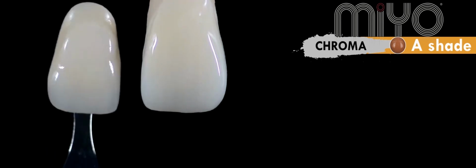Okay, and I'll be using translucent A here. You could see me float the color on top of the existing glaze paste. So there's different methods of MiYO application. Here I'm showing one application method by putting a thin layer of glaze paste before all the colors, because my intention is to glaze and finish everything with one shot. So you could see the color application is more of a dab and drag application, more of a paste opaque.